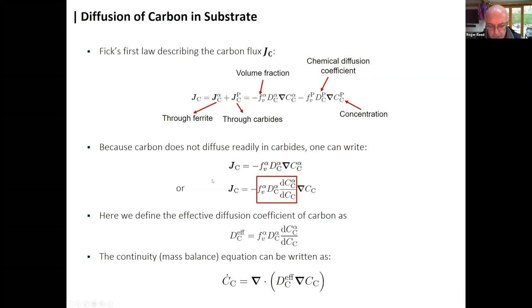And I won't go through all of the details of the mathematics, but in the end, what one has to think about is the effective diffusion coefficient of carbon in the system, which is proportional to the diffusivity of carbon in ferrite, but also of relevance here is this differential term here, which is the rate of change of the carbon concentration in ferrite with the net carbon concentration. And it's this effective diffusion coefficient which has to be inserted into the diffusion equation here for the treatment of this problem.